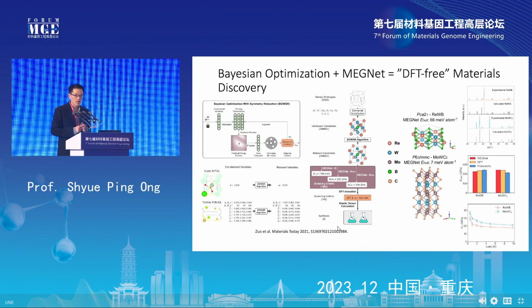Now, to show you that this actually works, I'm going to show you one of the prime examples where we actually managed to go from a machine learning model prediction all the way to an experimental synthesis of a completely novel material, right? So the target application is actually ultra incompressible materials. So what we did was to basically take ternary prototypes, about 5,000 ternary prototypes, and we basically put in a bunch of different elements, okay, molybdenum, tungsten, osmium, and rhenium, as well as boron and carbon. We generated about 400,000 potential crystal structures, and then we use this Bayesian optimization process to basically relax them, and then use a machine learning model to predict things like its stability, the bulk modulus and shear modulus, and then we do a preliminary screening, which then results in about 1,000 materials, which we then use DFT calculations to confirm.